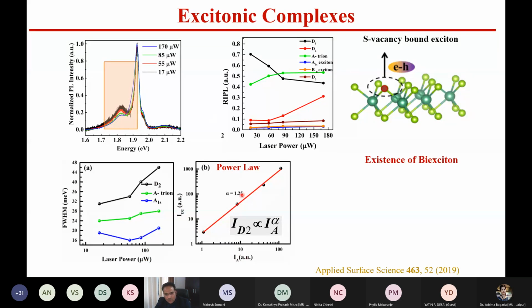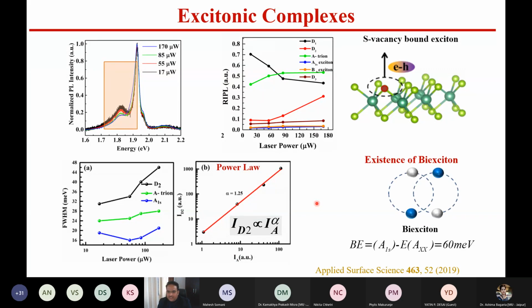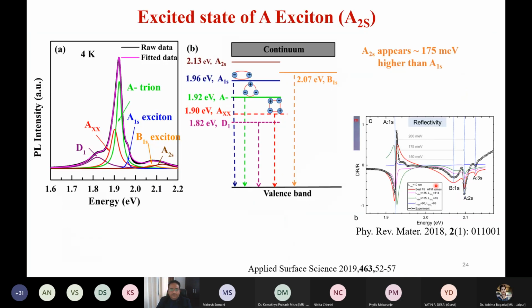If the slope of this curve is more than 1, or between 1 and 2, then there is an existence of the bi-exciton. If you have a large number of excitons in the semiconducting material, they might interact with each other and form the bi-exciton. This is a very interesting aspect of this research, where the existence of the bi-exciton up to room temperature has been proposed.